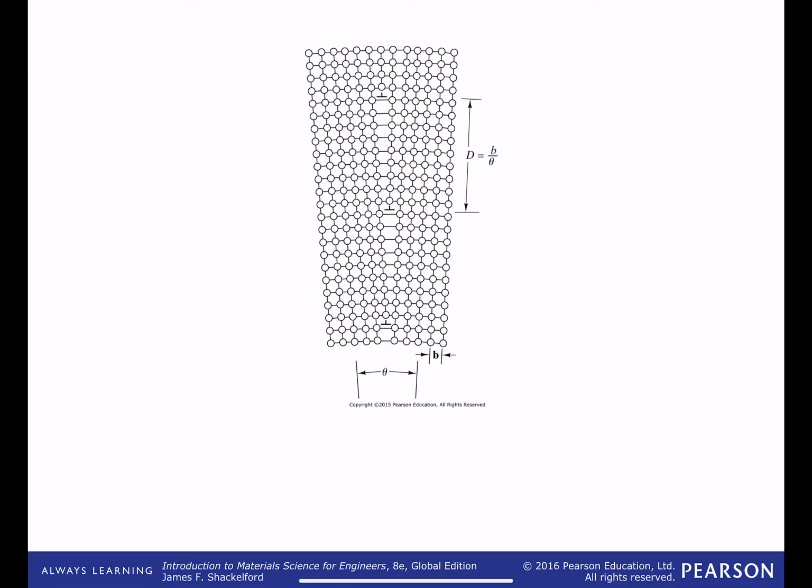The specific architecture at the grain boundary can be very complex, but in the scenario where we have a simple case where 2 distinct crystallites or grains are separated by what's called a tilt boundary, we have the concepts of our edge dislocations taking the space that's located in the grain boundary.